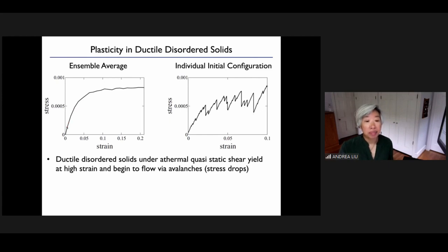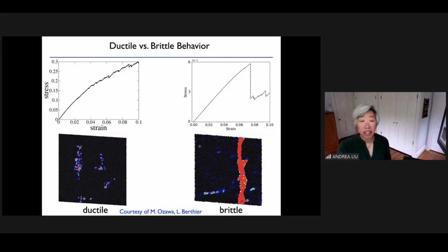Okay, so you have the stress strain curve. Initially the system responds elastically, but eventually it yields. This is the ensemble average over many realizations, but if you look at any given one, if you do this quasi-statically, so infinitely slowly, and at zero temperature, what you see are these individual stress drops. And each stress drop corresponds to not just a single localized rearrangement, but actually to an avalanche, a series of these rearrangements. And that's really what we'd like to understand.